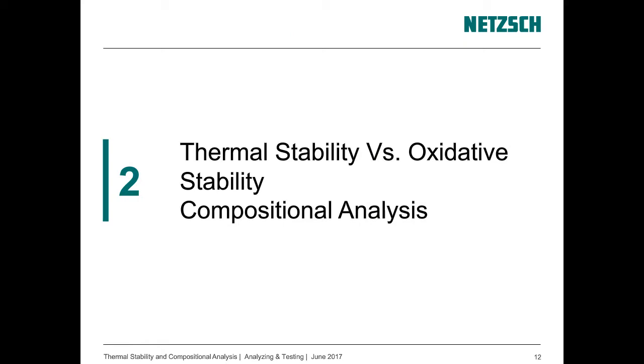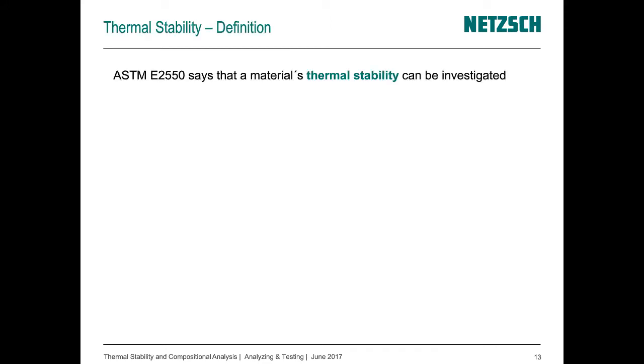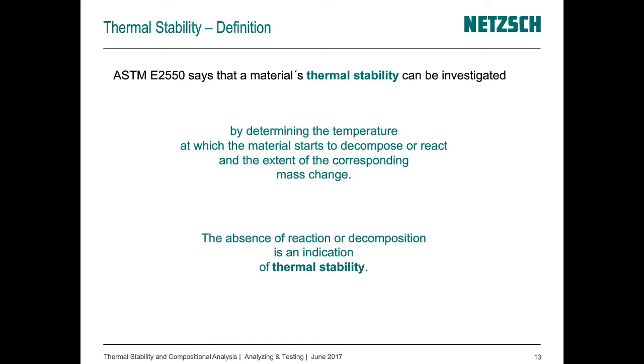And if we look at another standard, this time ASTM E2550, then we see the following definition: a material's thermal stability can be investigated by determining the temperature at which the material starts to decompose or react and the extent of the corresponding mass change. So that means there are two important quantities: the temperature at which the material starts to decompose, and the corresponding mass change. And on the other side, if nothing happens at all, then it's an indication of thermal stability.